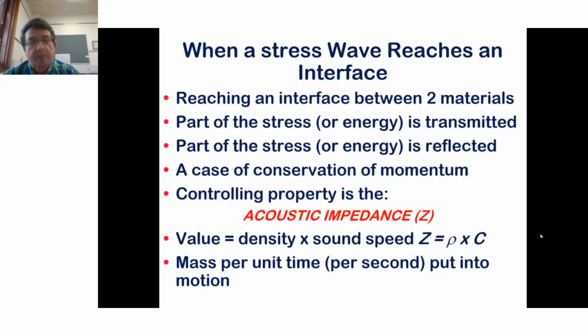What is the controlling property? It's a thing called the acoustic impedance in the elastic regime. And the acoustic impedance is the density multiplied by the sound speed. If you want to try and rationalize what this means, it's effectively the mass per unit time you can put into motion. And it is a material property. Density and sound speed vary from material to material. So acoustic impedance controls the transmission at interfaces.